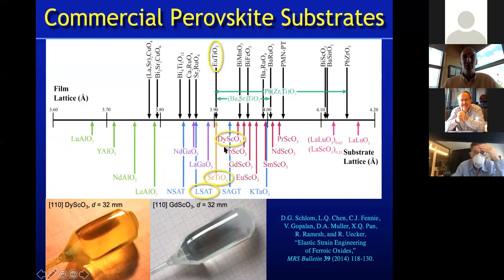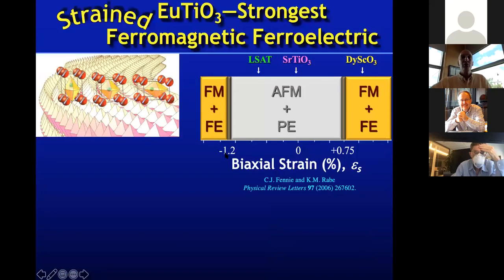with epitaxial strain. So I'm going to show an example that is putting europium titanate under biaxial compression on top of the substrate LSAT, about 1% biaxial compression, and also about 1% biaxial tension on top of dysprosium scandate. So first of all, what does theory say should happen? And like the theory that I showed you in the last slide, this theoretical prediction was also a prediction.